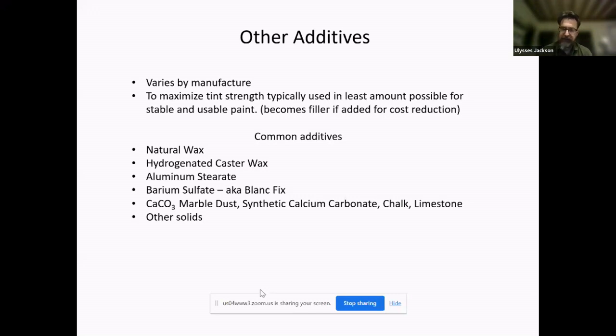The Blanc Fix, marble dust, and other solids would be used either to shorten up a very stringy paint. Like if ultramarine blue is made with just oil and pigment, it's almost unusable because it's so stringy and very flowing. So you might use just a tiny bit of some of those materials to get it to where it's a nice, buttery, good feeling paint, usually in the least amount possible. And then other solids, which that list could be quite broad depending on if you want textural effects or something like that.